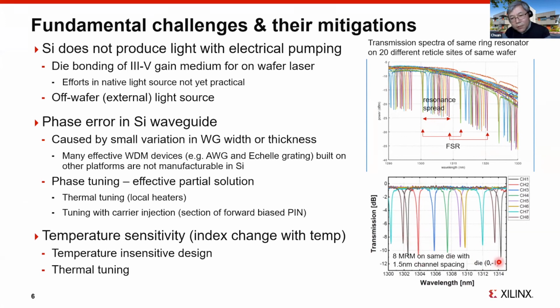So at the bottom here are 8 different micro-ring modulators. We design them to have equal spectral resonance wavelength separation. You can see that you don't really achieve uniform spacing, but all these channels are at least in the right sequence. In a real situation, we apply thermal tuning to all these devices, then we can even equalize the channel spacing.